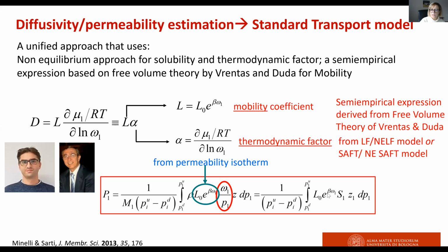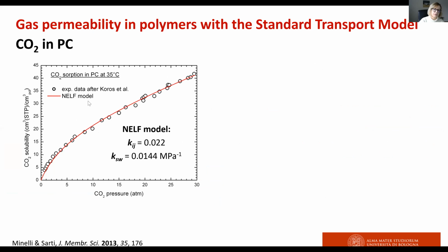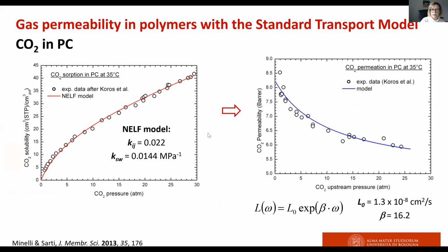This theory contains two adjustable parameters that are L0 and beta. And the model performs very well because from the parameters obtained from the modeling of the absorption isotherm, you can easily estimate accurately the trend of CO2 permeability in the same polymer, which in this case is polycarbonate at 35 degrees. And the model can also predict the presence and occurrence of a plasticization pressure, which has to be avoided during membrane separation processes because it leads to a loss in performance.